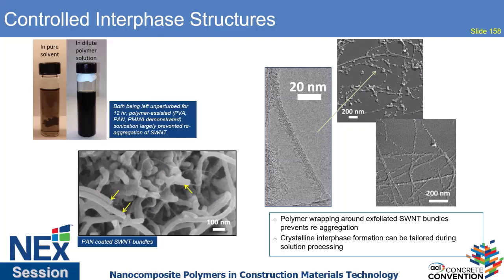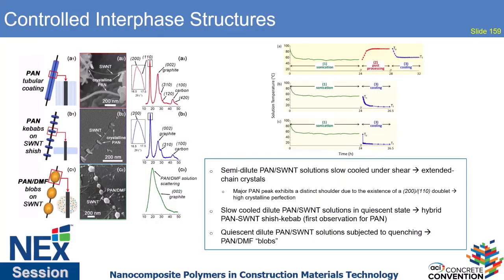And we found that if we disperse these by sonication and add some heat treatment, we could create various coatings around the nanomaterial, but this is not using any phase separation method, so you're just kind of getting what you're getting. And this was nice because we could learn about sonication, we could learn about using different heat treatments, post-processing, even using some shearing, and we could cool it, undercool it, control crystallization. We could look at when we got very nice tubular coatings versus shish kebab coatings versus nothing that's very special.